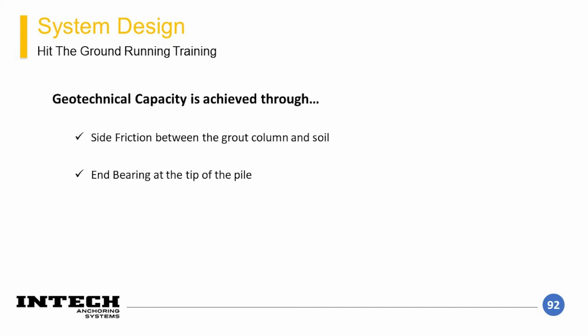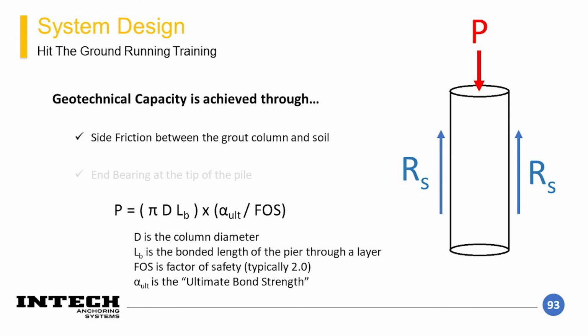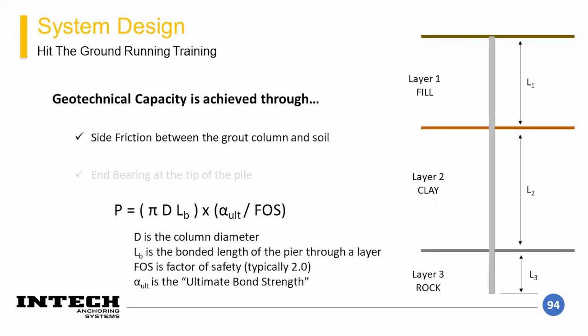So with geostructural solutions, there are a few things to consider. First, I'll go through the major principles for the geotechnical capacity. The geotechnical capacity is comprised of two things: the skin friction and end bearing. The side friction is generally taken along the surface area of the sides of the grout column diameter. So we would take this area, which is a function of the diameter of the bit, and multiply that by the bond strength. There's also a factor of safety applied to this bond strength, so it can be compared to a design load. This area times a strength results in a resisting capacity.